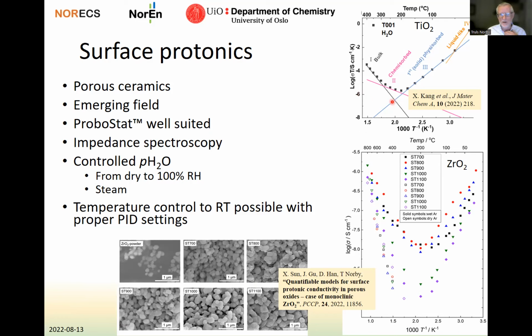Here are some examples. Here is a recent paper from this year by Shalan Kang and co-workers from my laboratory in Oslo, where she has measured bulk conductivity and the conductivity in the chemisorb layer and the first physisorb layer and the liquid-like physisorb layer as a function of temperature. And these are then protonic surface conduction on a sample of TiO2. You can see that you go very close to room temperature in these measurements, typically. And I would like to point out that temperature control all the way down to room temperature, even with big furnaces, is possible with a ProboStat if you set the PID properly on your temperature control.